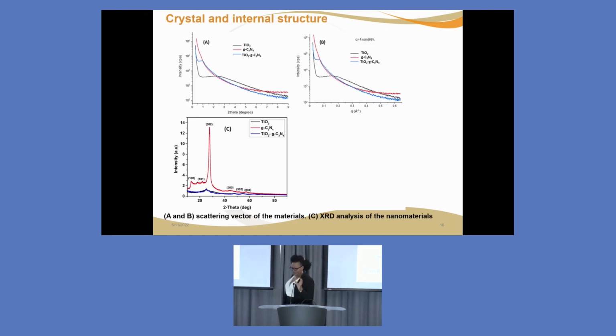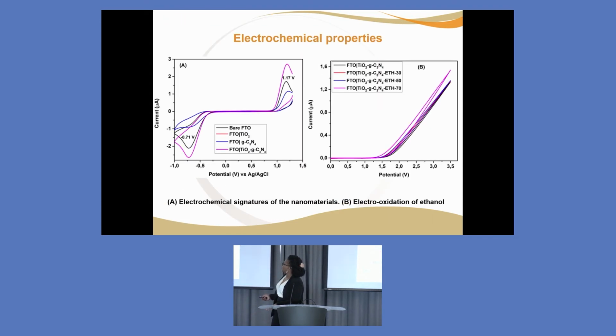And also because it is important to monitor the crystallinity or the internal structure of the material. So in this case, we combined the small angle X-ray scattering, because the small angle X-ray scattering will talk about the internal structure, the shape and the size of the material. And if you are combining it with the X-ray diffraction, that is referring to the crystallinity of the material. So we can see, if you're looking at the peak here, this is the combination, the nanocomposite. I'll just focus on the nanocomposite here. We are seeing a sharp peak at around 2 in both cases. And we are seeing some changes in the crystallinity here when they are combined. It means that the nanocomposite we have formed are crystalline in nature.